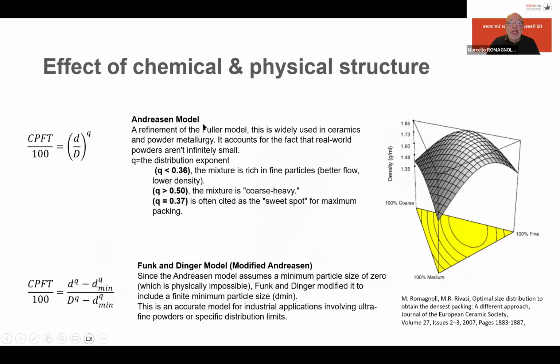These are just two of the most used, the Andreasen and the Funk-Dinger models. They work, from my point of view, very well if the real particles are similar to spheres, but they don't work so well if the particles are not spherical. In this case, in my experience, approaches like design of experiment are better because they consider also the real shape of the particle.